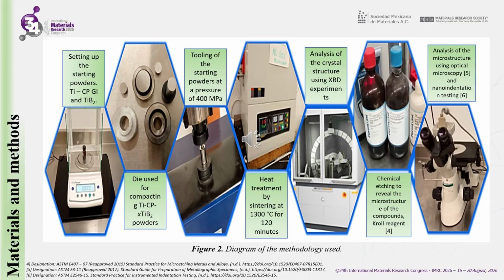In order to prepare each composite, a mixture of commercially pure titanium grade 1 powders and titanium diboride particles was created, with varying concentrations of the former component ranging from 0 to 15% by volume, and the latter from 0 to 10% by volume. The mixtures were subjected to a compaction furnace at 10 to the power of -4 millibars. The heating ramp commenced at room temperature and increased at a rate of 5 degrees Celsius per minute until reaching 1,300 degrees Celsius, where it was maintained for a duration of 2 hours. The composites were subjected to cooling within the furnace.